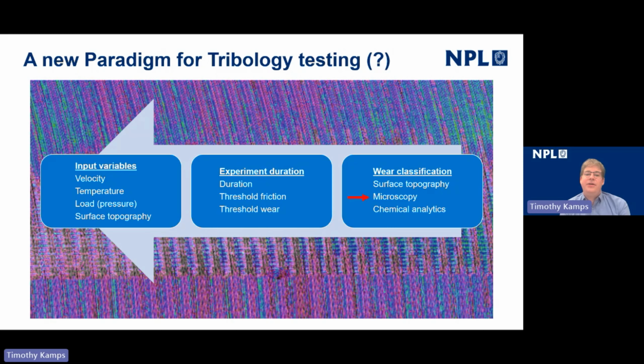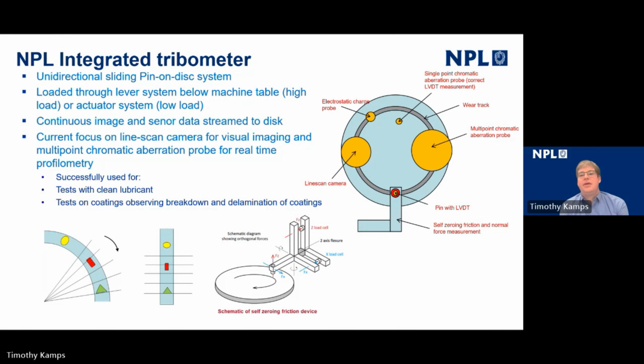And in this way, we can dramatically reduce the number of tests that we need to do in order to precipitate the failure mode of interest for the study. So this is implemented at NPL using our unidirectional sliding tribometer or pin-on-disc test system.